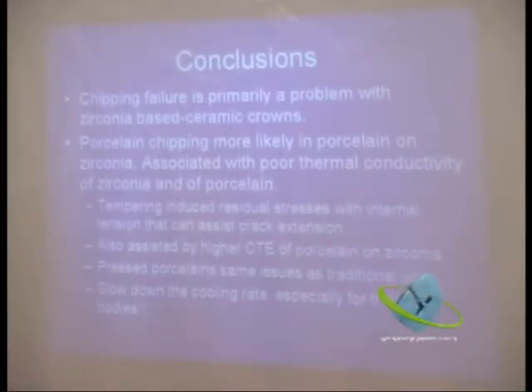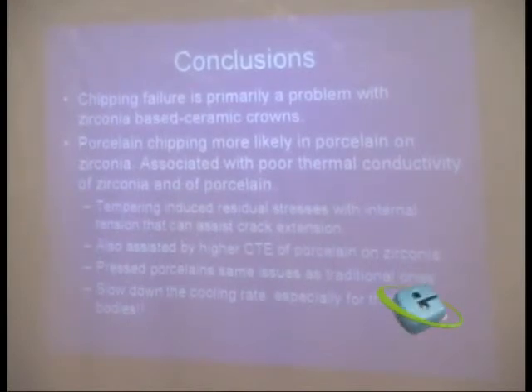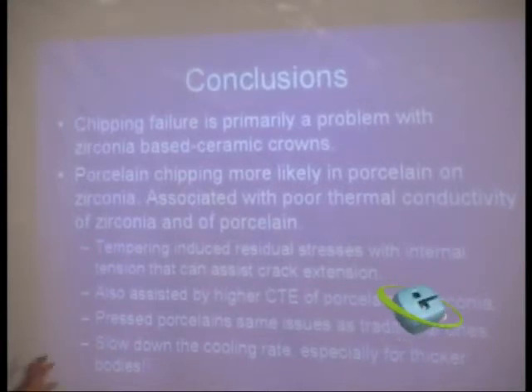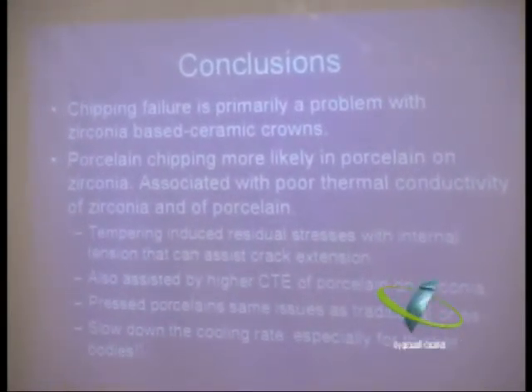Alright, I think I'd better stop at this point. These are my general conclusions. Chipping is a major problem, but it is relatively easily solved, provided that the technicians and companies acknowledge the cause. It's only really a problem in zirconia-based systems because of the poor thermal conductivity. That does not mean it does not happen in other materials. If you have poor design, you can still get chipping. But the likelihood of chipping is much greater with zirconia. This is due to the tempering stresses in that system. It's also assisted, and I didn't talk too much about this, by the high coefficient of thermal expansion. The higher the CTE is, the greater the stress that develops. Pressed porcelains have the same problem as traditional systems, so really slow down the cooling rate, particularly for thicker systems.